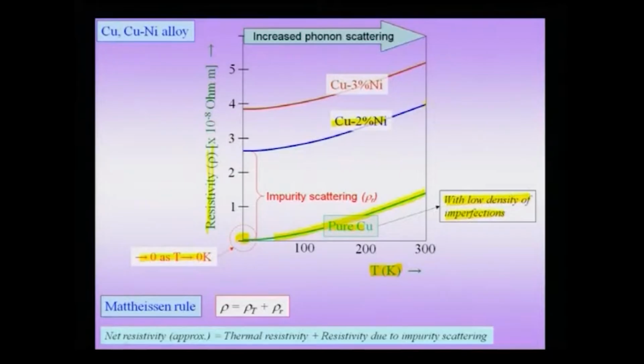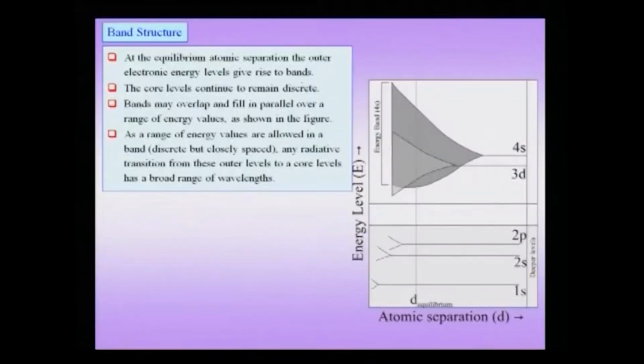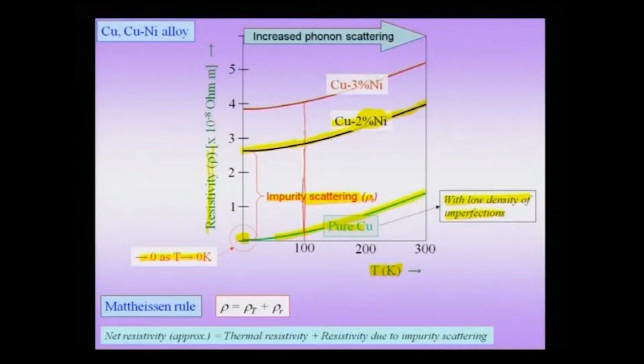This alloy, even though the resistivity decreases with temperature, which is what we expect because the phononic contribution is going to decrease, there is always a residual resistivity even as we tend towards 0 Kelvin, and this is coming from the fact that now you have an alloying element like nickel, which is going to give rise to what you might call the impurity scattering or the alloying element scattering. And as you increase the amount of alloying element, say now suppose I am at a particular temperature like about 100 Kelvin, you would notice that my resistivity increases as you add the alloying element, and you add a little more of the alloying element, the resistivity further increases. That means, with more and more alloying element, you are going to have higher and higher residual resistivity as you tend towards 0 Kelvin.